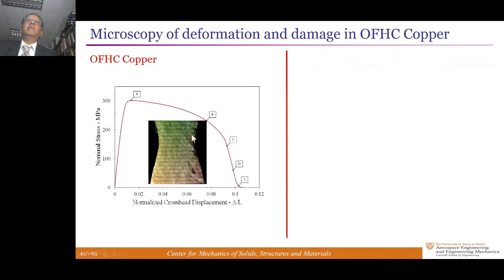So let's start with the copper. At the point A, necking localization occurs, but you really don't see any change in the structural dimensions of the specimen at large scales. At B, this is what the cross-section of an initially straight specimen looks like. This is the neck that has formed. And these are high-resolution microscopic images of the grain structure that have been assembled together into one piece. They're made out of 200 microscope images in one piece. These were done in the days when automatic stitching of these things was not available, but since that time, the technology has improved to do this in very short order.